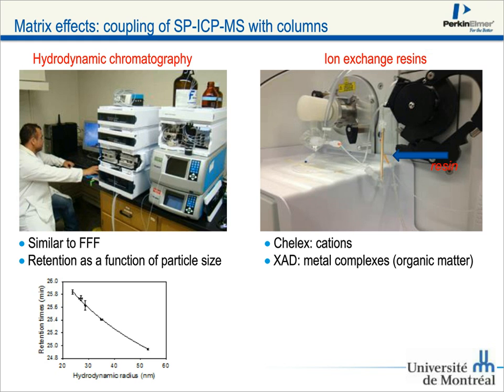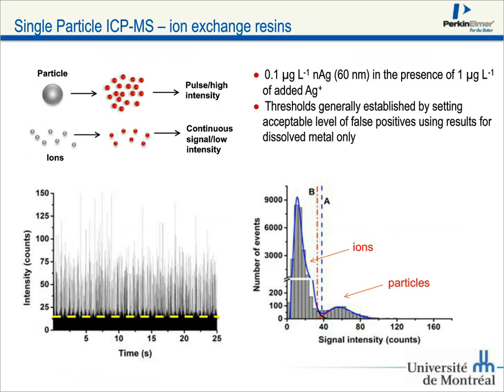You get retention times, with the particles coming out at different times based on their radius. The other thing that we're doing is coupling the ICP-MS to ion exchange resins. So, for example, to Chelex resins, where you're removing the cations, to XAD resins, where you can remove a lot of the organic matter. You see here the resin in the figure on the right. What that does, as Shadi explained to you earlier, is address one of the problems associated with single particle ICP-MS, which is setting the threshold level, distinguishing between what's dissolved and what's particulate.